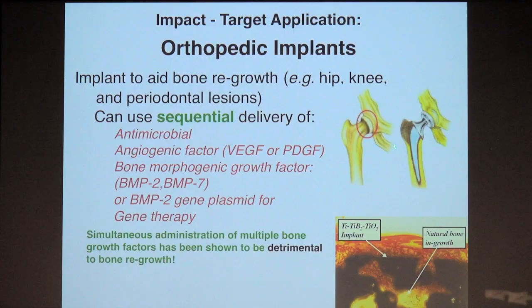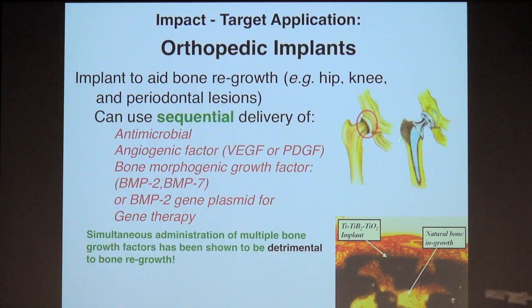Now, what happens when we replace that hip joint? Here you can see where the ball and joint go in a titanium hip replacement. This is the ball, and here is where we insert the implant into the femur. It turns out that if you have a replacement, you worry a lot more about infection than you do in the original operation. And the reason for this is that there's been plenty of time for bacteria to find their way into the crevices here as this begins to wear down in the body.